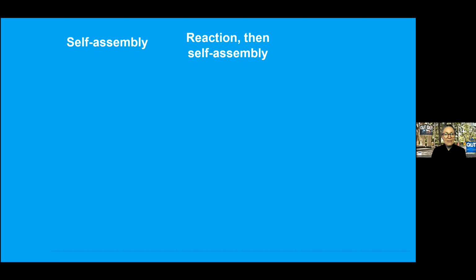But we can also look at a process where we change the building block on the surface and then allow that slightly modified building block to self-assemble. And of course, finally, we can look at allowing a reaction on the surface that leads to covalent bonding. Rather than these non-covalent interactions, we can allow for strong bonding to occur. Generally, what we're looking at in the surface science experiments of typically planar aromatic molecules is a carbon-carbon bond formation.